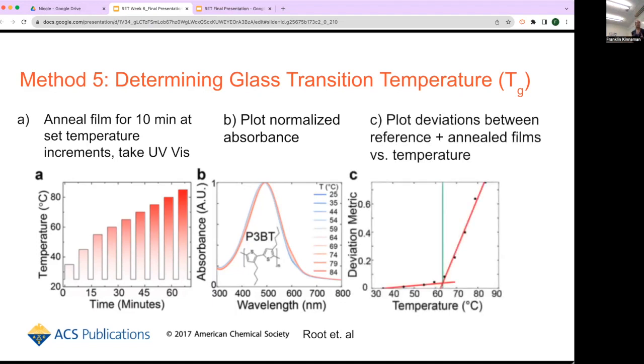And finally, the fun part, actually extracting the Tg from this data. Essentially what you're seeing here on the y-axis, the deviation metric, is just the fancy way of putting the difference between all of the points on our reference curve and all of the points at each temperature's curve above it. So for the 40 degrees point, you'll see it's calculating the overall deviations between room temperature and 40 degrees. For 50 degrees, it's the difference between room temperature and 50 degrees, and so on and so on. What you start to see in this example is that at 65, our trend line drastically changes into a really, really steep deviation from room temperature. And the point at which these two best fit lines intersect is our glass transition temperature.